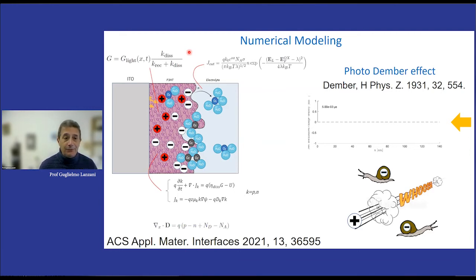The other thing to consider is that the negative charge is interacting with oxygen easily, and that water is also helping, hydrating the charges. So we have polarons, which are formed in this diffuse interface in which the polymer is mixed with islands of water, oxygen, hydrated oxygen, superoxide. So it becomes a system. So this part is the heart of our device.